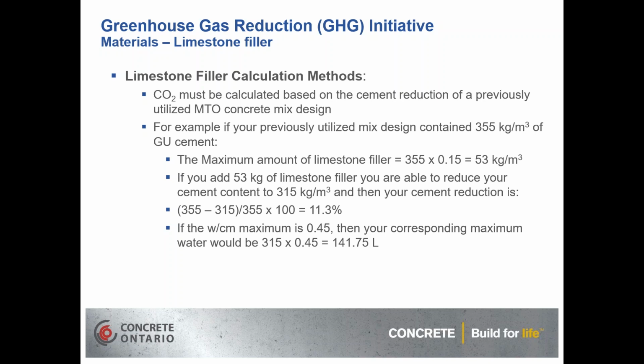So if we added those 53 kg of limestone filler to our concrete, and we found that we were able to reduce the cement content down to, for example, 315 kg per meter cubed and still meet the same strength, water cement ratio, and durability parameters, then the cement reduction would be 355 kg minus 315, divided by 355, the original cement content, times 100, would give us a reduction of approximately 11.3%.